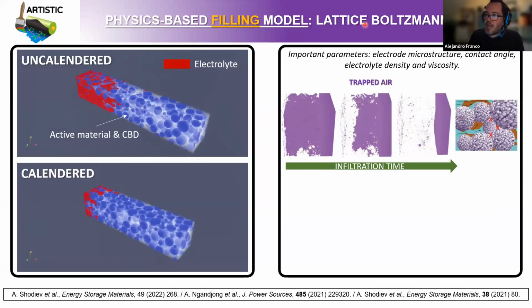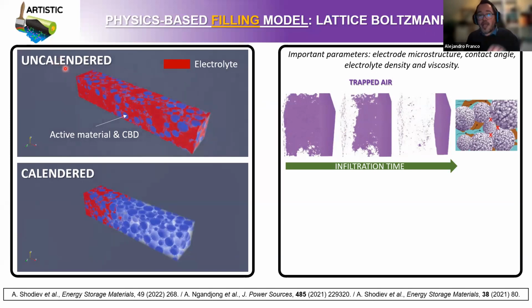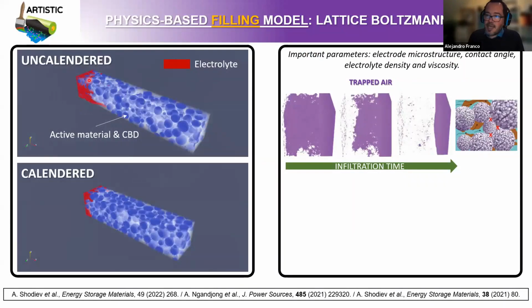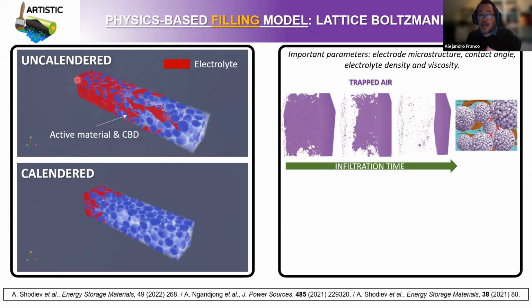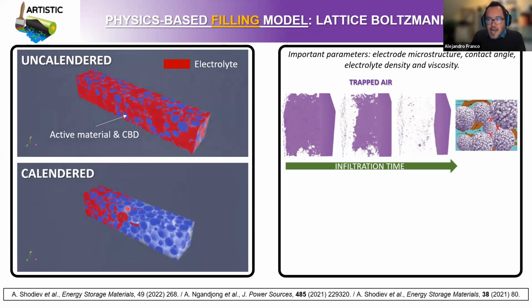Here you see simulations that we have performed by using the lattice-Boltzmann method technique to predict the trajectory of the electrolyte when it's being infiltrated into electrodes, an uncalendered electrode and a calendered electrode. So you see how fast is the infiltration of an uncalendered electrode, and how slow is the infiltration by liquid electrolyte of a calendered electrode. The reason is that a calendered electrode has higher tortuosity factors. Porosity is lower, tortuosity factor is higher. Therefore, there is a more intricate path for the liquid electrolyte to go into the pore network. While for an uncalendered electrode, porosity is higher, tortuosity factor is lower, so it's easier for the liquid electrolyte to go and to fill the pores, right?